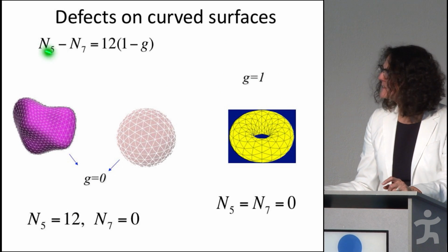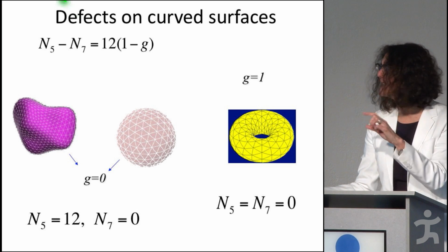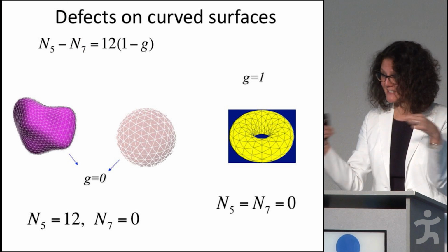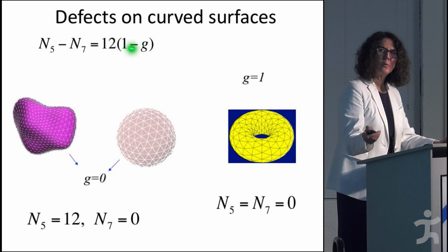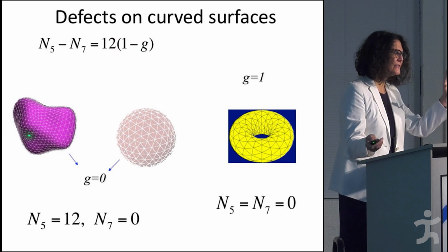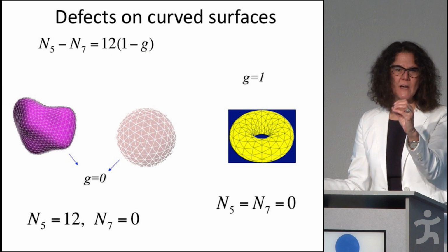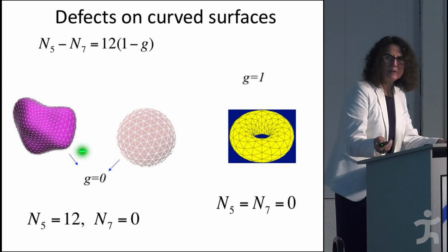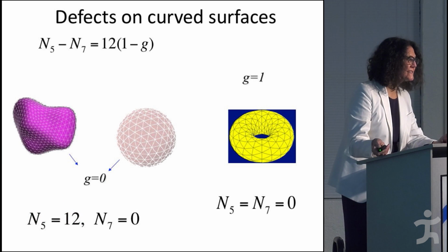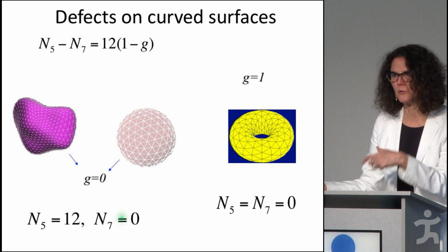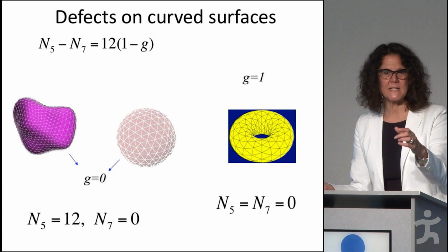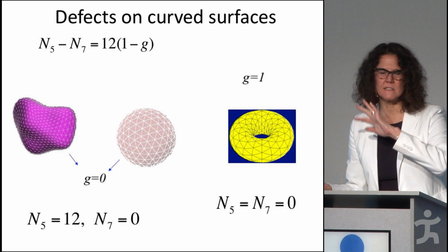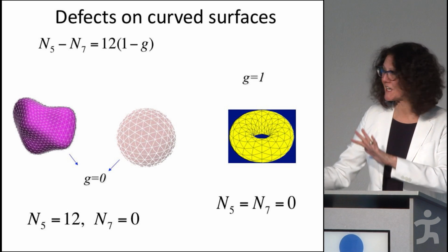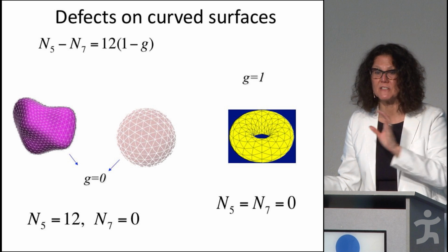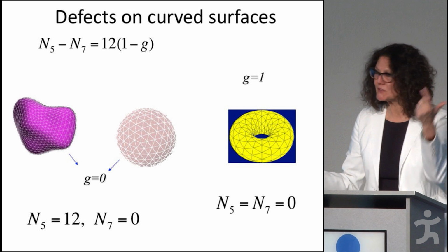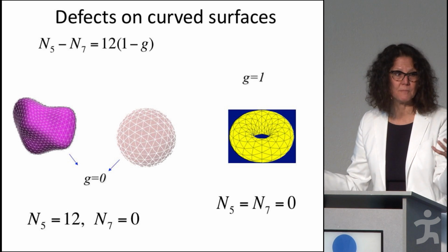And the minimum number is that the number of pentagons minus the number of heptagons, that have 7 nearest neighbors, has to equal 12 times 1 minus the number of handles the geometric object has. So a sphere has no handles, so it has G equals 0. So the minimum number is to have 12 defects that are pentagons and 0 heptagons. If you were having 13 pentagons, you need a heptagon to cancel it. This is a theorem. And it doesn't matter if it's a sphere or another shape, if it's closed, it has to have these 12 defects, these 12 pentagons. So now I'll tell you what the pentagons do. That's the one that leads to the buckle.